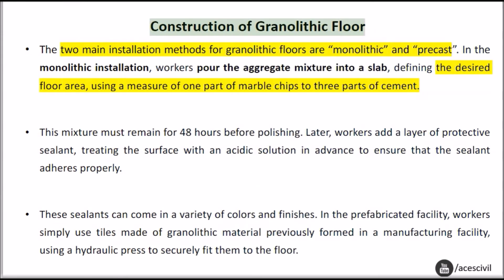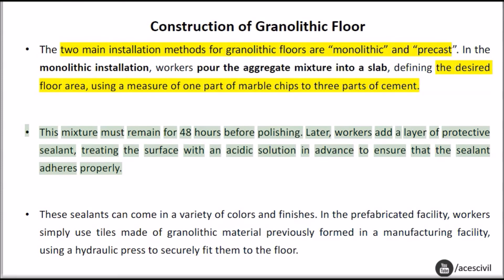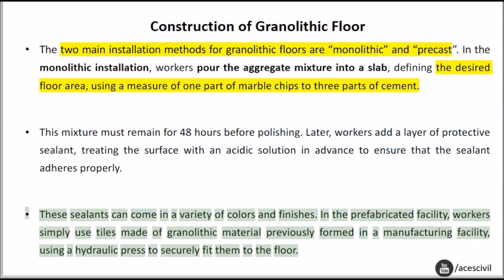Construction of Granolithic Floor: The two main installation methods for granolithic floors are monolithic and pre-cast. In the monolithic installation, workers pour the aggregate mixture into a slab defining the desired floor area, using a measure of one part marble chips to three parts cement. This mixture must remain for 48 hours before polishing. Later, workers add a layer of protective sealant, treating the surface with an acidic solution in advance to ensure that the sealant adheres properly. These sealants can come in a variety of colors and finishes.